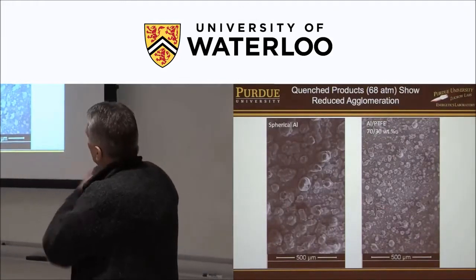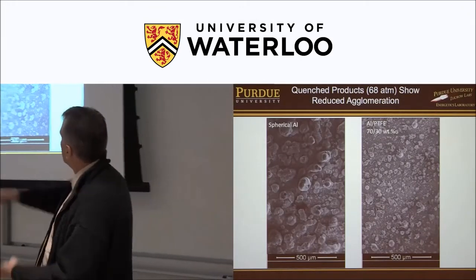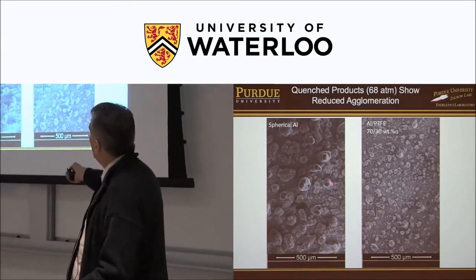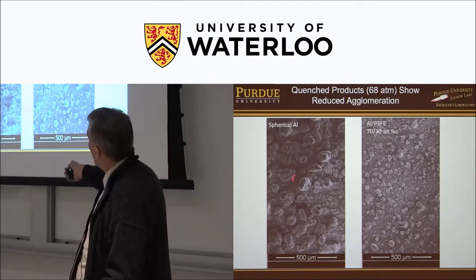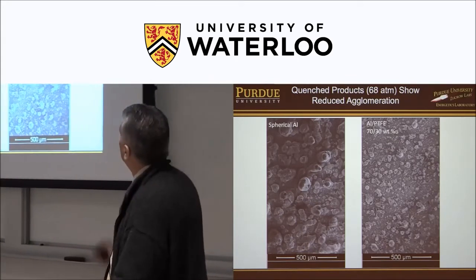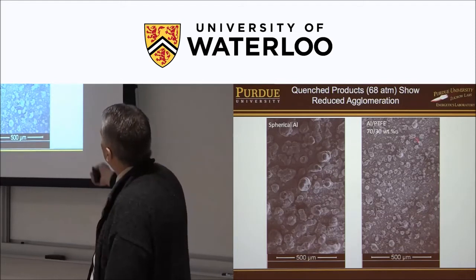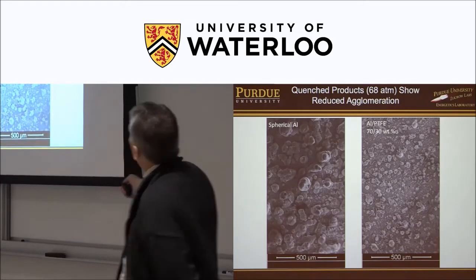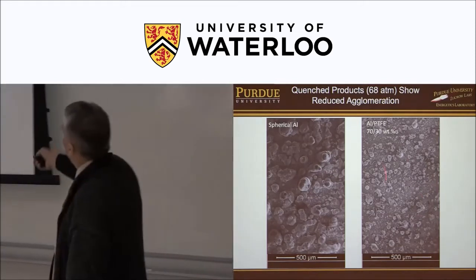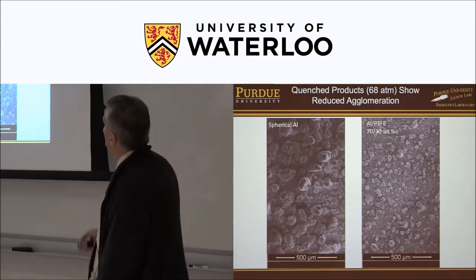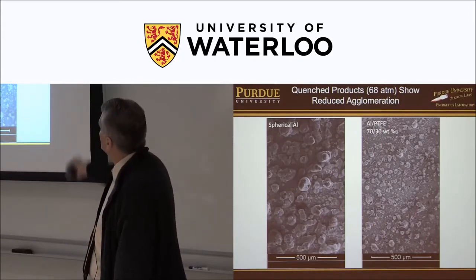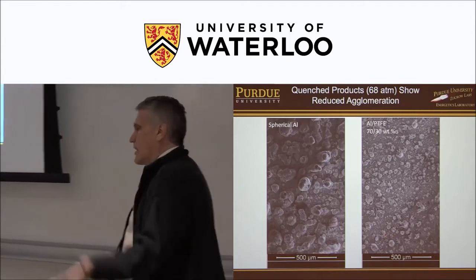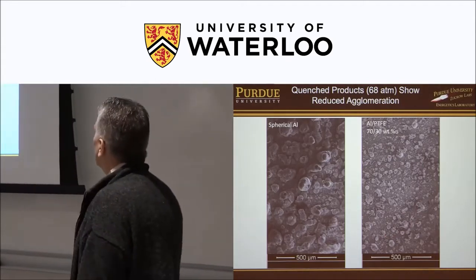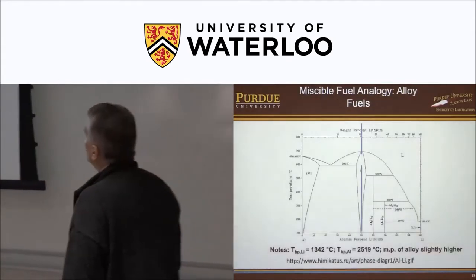This just shows some, we burn strands and collect the particles. This is the baseline propellant, and you can see large alumina particles that we collect. For the modified, this mechanically activated material, you can just visibly see, and we've quantified this, of course, there's a lot smaller products. Smaller products will result in lower two-phase flow losses and better performance for your rocket.